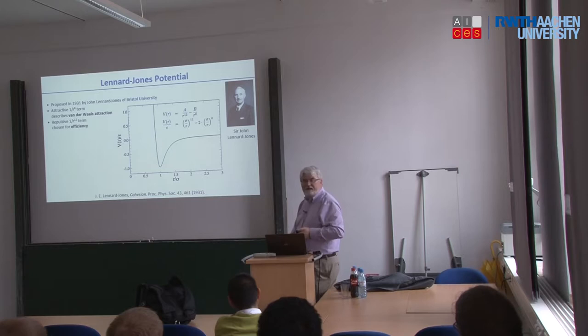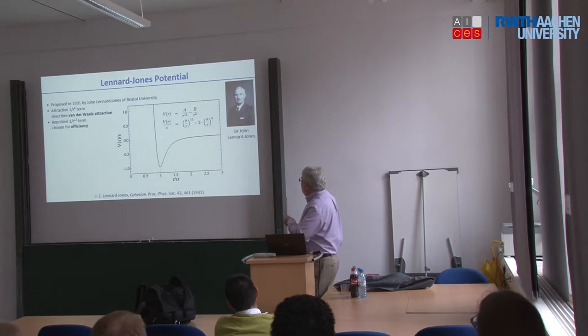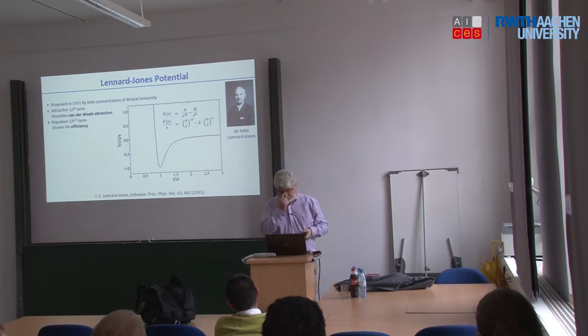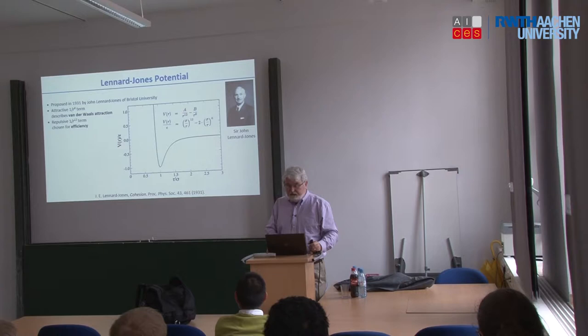So you write down this equation, and buried in here, this is some kind of energy, and this is some sort of distance to make the units all work out. So this is what it looks like. And you can put that into an MD code. It's very easy to do. And you can actually simulate an ideal gas. And this was actually used for many, many years to simulate metals as well, because we didn't have anything better until the mid-80s.